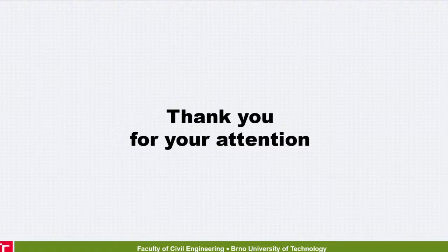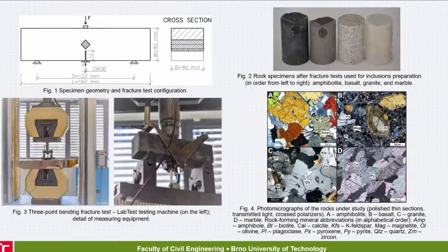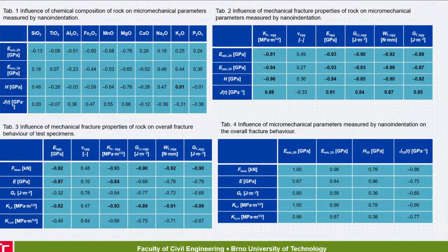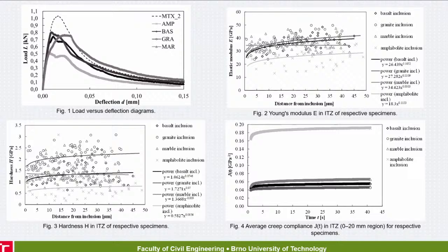I observed scattering of the experimental results, and then you mentioned that you determined some properties by nano-indentation. Yes. If I understood correctly, the material is inhomogeneous, definitely inhomogeneous. Yeah, the matrix is homogeneous. So this slide, the one with the scattering, what is the correlation between the curves drawn? The scattering is huge in the previous slide. You mean which one? The previous one. You have some experimental points. Yes, yes. And some curves. Are the curves based on curve fitting of the experimental results? Yeah, what is the coefficient of correlation between the curves and this cloud of points?